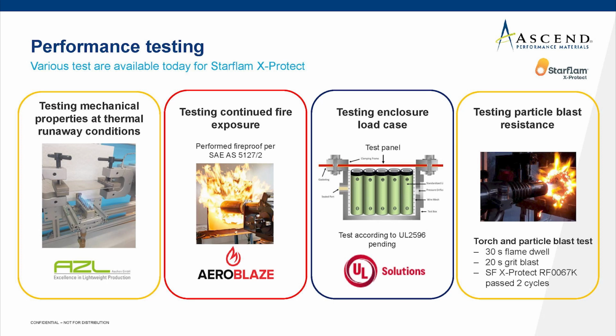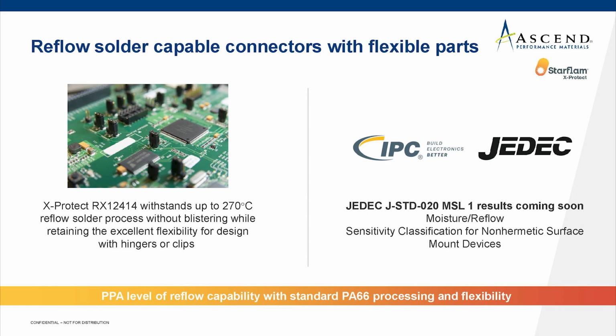With this, we conclude what we have about thermal runaway, but I also want to give you some hints how you could use X-Protect in a different context that can still be automotive, but doesn't necessarily come with these extreme temperatures. Another application space can be in the context of reflow soldering. Think about a cable to board connector and the board connections of electronic components, and those connections are generated by reflow soldering. You want your molded connector to withstand this reflow soldering temperature level throughout a time of 10, 15, 20 minutes, depending on how you establish your solder process, without, first of all, deformation.